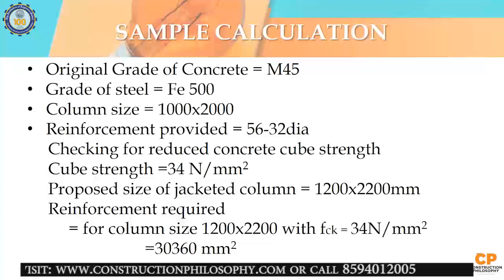So these were the different processes. The original grade of concrete was M45. How do we solve this problem? Grade of steel Fe500, column size 1000 by 2000, reinforcement provided 56 bars of 32 mm. Checking for reduced concrete cube strength, we found that only 34 Newton per mm square was there.